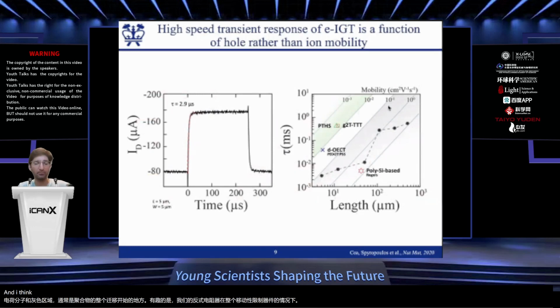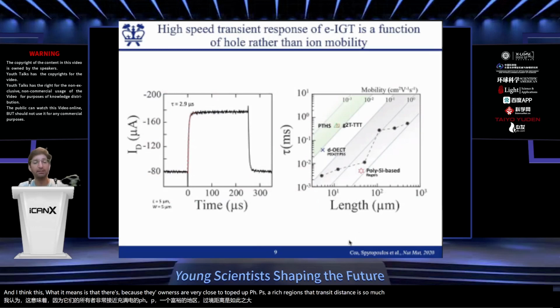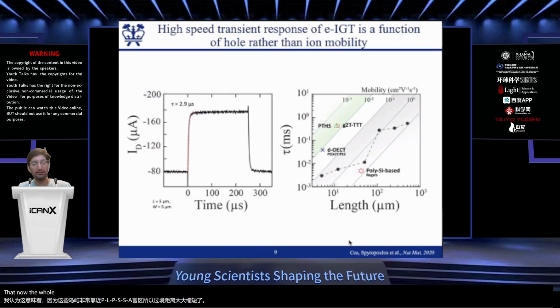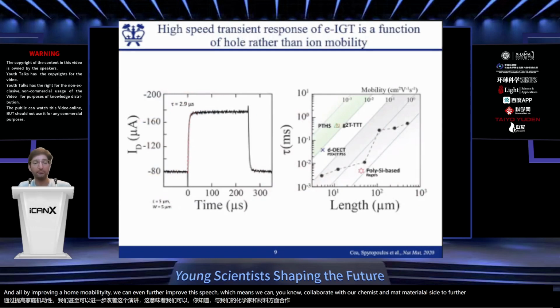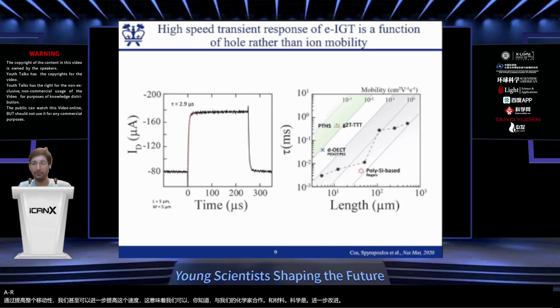And I think what it means is that because the ions are very close to the PSS-rich regions, the transit distance is so much reduced that now the hole mobility is the limiting factor of this process. This is great news because a physical barrier in the device dynamics is broken, and by improving the hole mobility, we can even further improve this speed, which means we can collaborate with our chemists and material scientists to further improve our device performances.